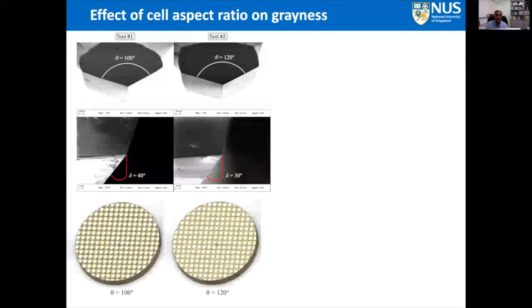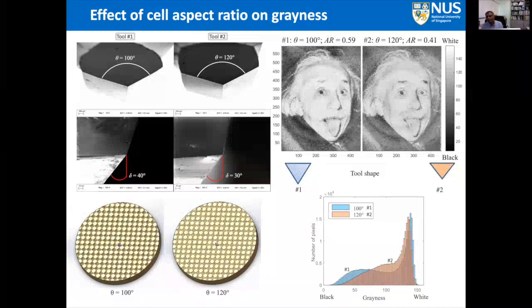Having developed this technique, we wanted to explore how the image behaves at different tool geometries, and to have an understanding of the whole process. The resolution of the images, what you see at the top, is 430 by 560, with a total of approximately 240,000 pixels. A distinct difference in the contrast level between the two images is seen here. The darker and sharper pixels are found at the corresponding locations for micro images machined using tool 1 compared to tool 2. When you use tool 1, you see a better image, while in tool 2, the image is not of good clarity. That is obviously seen here.